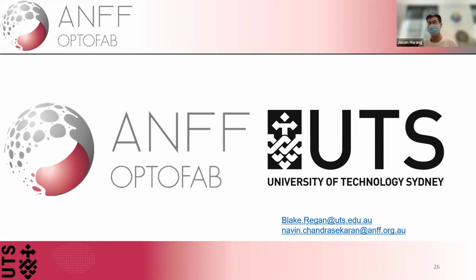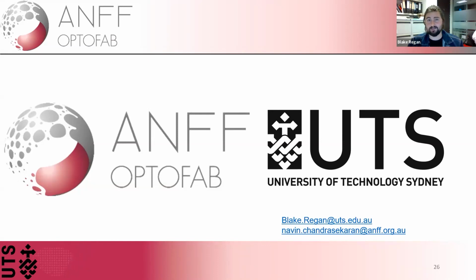HSQ, as good as it is, don't use it on insulating material, and don't use it when trying to achieve anything less than 50 nanometers. There are better materials for that. But I even looked at a paper yesterday where they actually created silicon dioxide waveguides just out of directly writing them out of HSQ with nanodiamonds just housed inside the HSQ to create integrated photonic circuits. So it's a powerful tool, but it is obnoxiously annoying to get into the country.